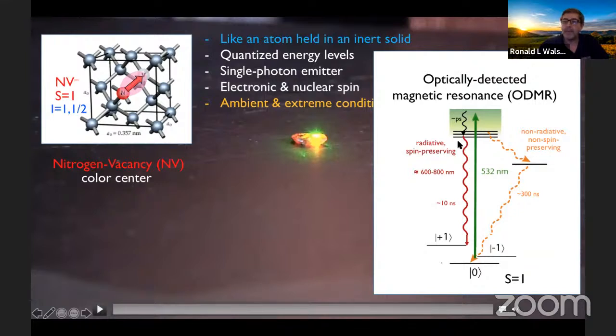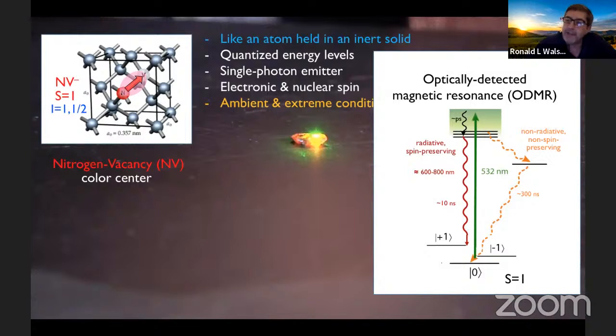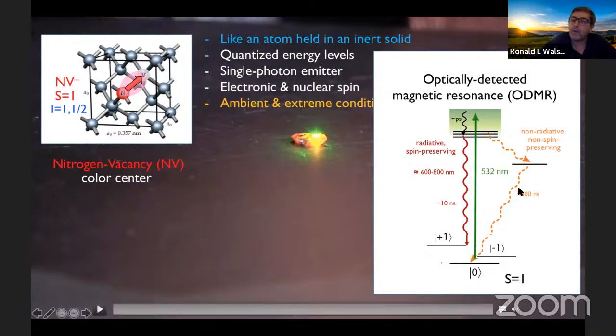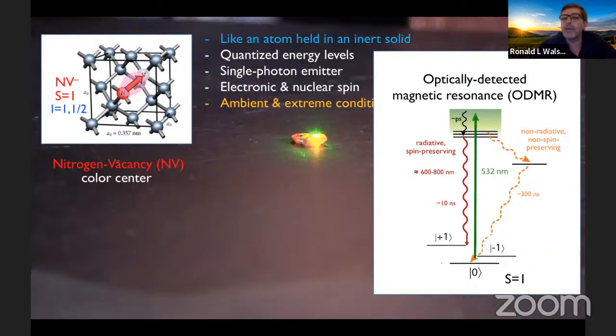That's a radiative decay. That whole process, the decay in the picoseconds and then the nanosecond scale fluorescence, tends to be spin preserving. So if you start in the m=0 or plus or minus 1 levels, you'll absorb a green photon and emit a red photon and return back down to the level you started from. But the second decay process, shown with the dashed wavy orange lines, is a non-radiative spin-changing decay due to the modest spin-orbit interaction that exists in the excited band here. So it's non-radiative, non-spin preserving, and happens over several hundred nanoseconds. And it tends to be favored for the plus and minus 1 levels and tends to change their spin in the process of decay down to m=0.